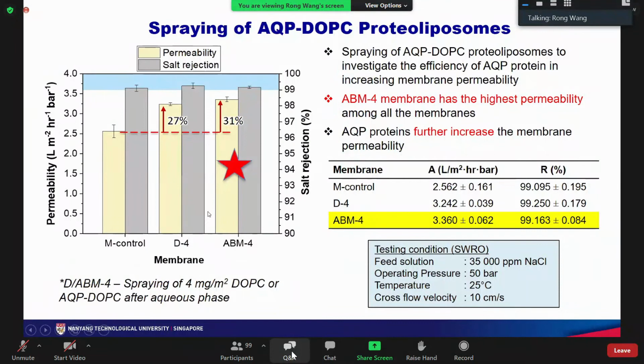Look at the performance. Now we get membranes with water permeability 3.36 LMH per bar. The salt rejection is over 99%. The enhancement compared to the control membrane is over 30%, while maintaining very high salt rejection. This result is very exciting. Later, we do the PVA coating to enhance the antifouling property. At the same time, it can boost the salt rejection. The rejection can be further enhanced by sacrificing a little bit of the water permeability.